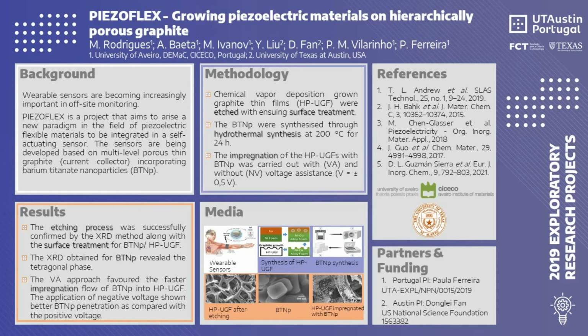Both the etching and surface treatment processes were successful, as indicated by the foam's XRD diffractograms and by the way the particles are clinging to the foam surface, indicating that it lost its super hydrophobicity. The crystallographic phase of the barium titanate particles is a tetragonal phase, confirmed by its XRD diffractogram, which indicates possible piezoelectric behavior.